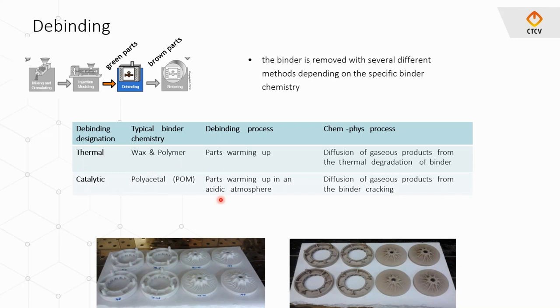We can remove the binder by a catalytic method. This is applied for binders based on polyacetal or polyoxymethylene. The parts are warmed up in an acidic atmosphere, but the temperatures here are more or less 100 degrees, whereas in the thermal way we go through 300, 400, 500, 600 degrees. So this is a quite quick method for removing the binder.